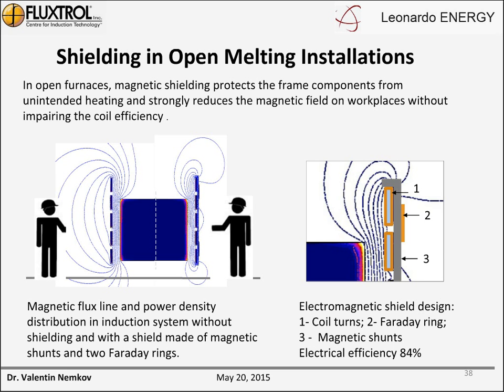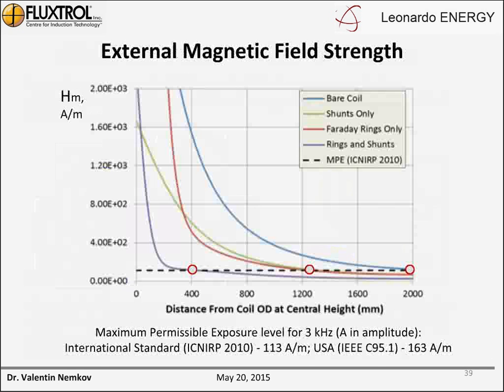So we can design and we can predict temperatures and so on. Here we have the resulting curves, the external magnetic field strength. You can see that for the bare coil, the blue line, we reach the maximum permissible level at a distance of 2 meters from the surface of the coil, which is too far. If we have the rings and shunts, the purple curve, this distance drops to less than 400 millimeters, which is very good. And only Faraday rings or only magnetic shunts are somewhere in between these two curves.